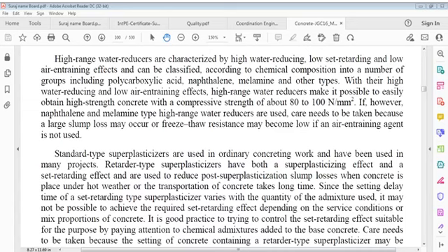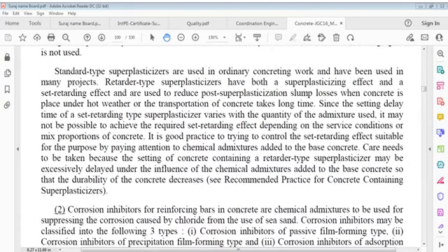If, however, naphthalene and melamine type high range water reducers are used, care needs to be taken because a large slump loss may occur. Freeze thaw resistance may become low if an air entraining agent is not used. That is, freeze thaw resistance may become low.